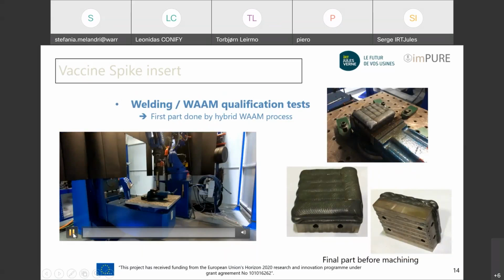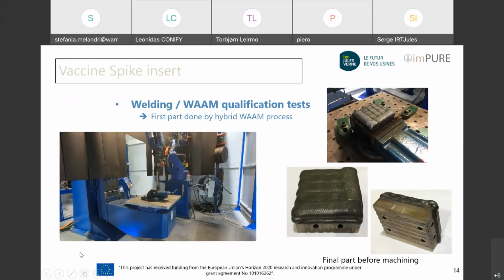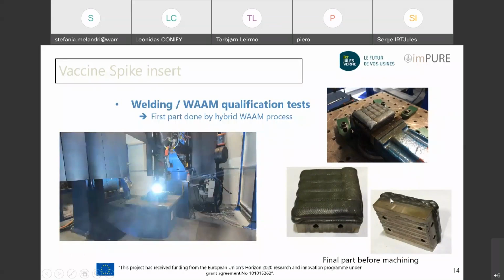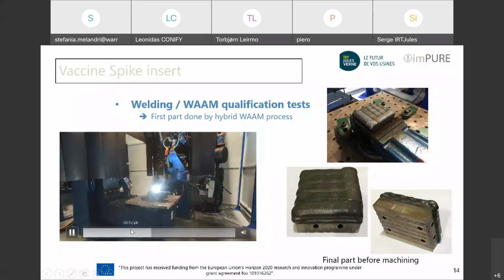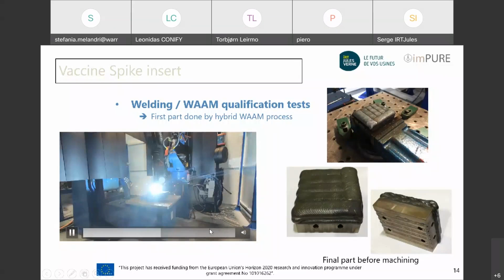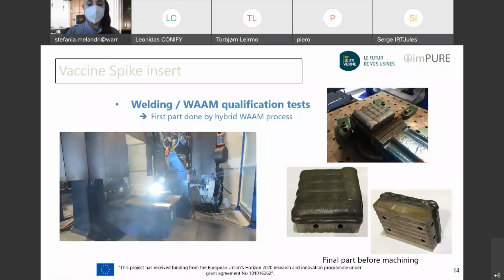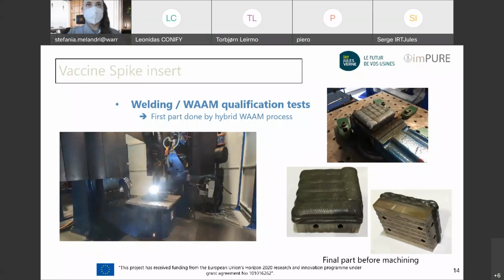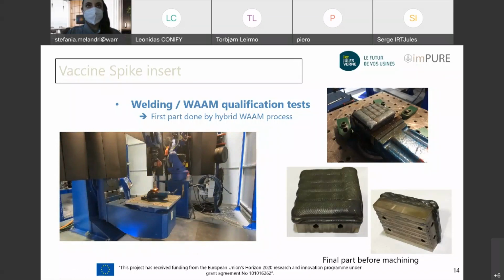So, just a small video, just to see the productivity of the process. You can see 5 beads and 1 transverse to reduce the extension. And here, as I say, we have the over thickness that was a few millimeters. And you will see it start around 15 seconds, and it will give you an idea of the productivity. So one bead was requiring less than half a minute, and with 20 beads in less than 10 minutes, we were able to produce the one. So you see, it is really very interesting about the productivity.